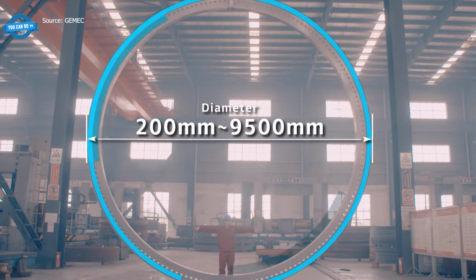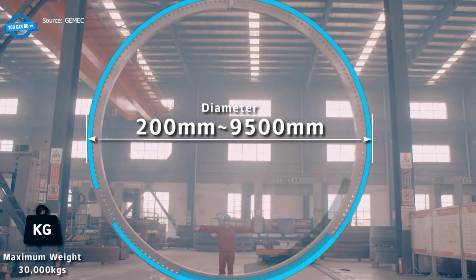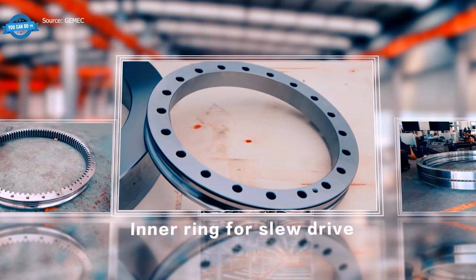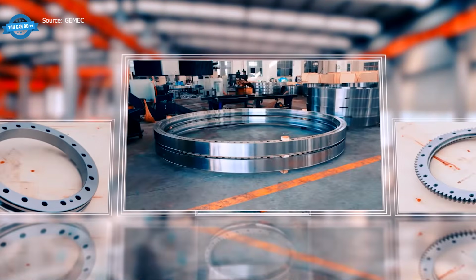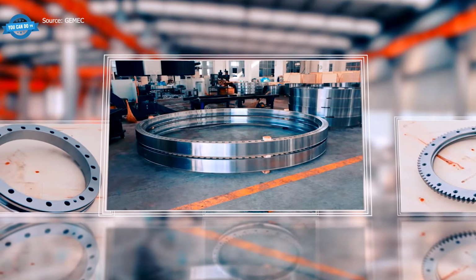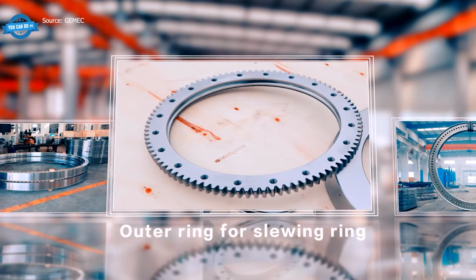Ring rolling scales in ways that get out of hand quickly. Diameters run from 200 millimeters up to 9.5 meters. Weights climb to 30 tons. Height up to 1.6 meters, width up to 1 meter. You could walk through the finished part without ducking, and that is before the ring gets machined into a wind tower flange, a slew drive inner ring, or a bearing outer race.